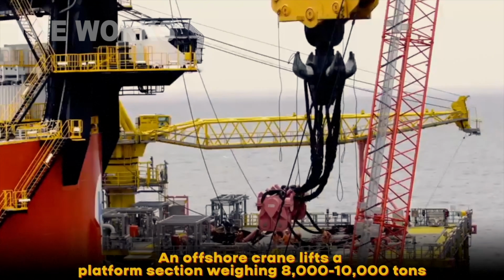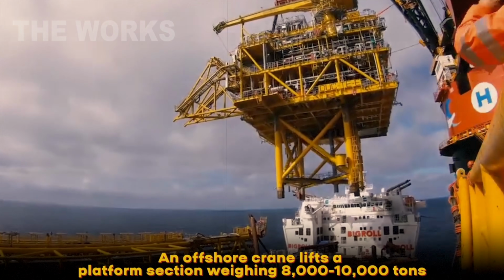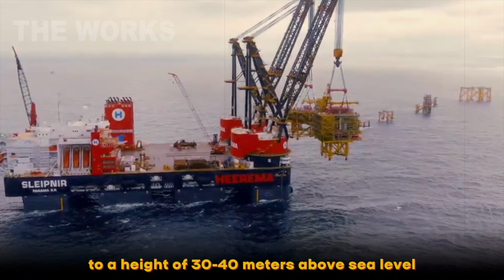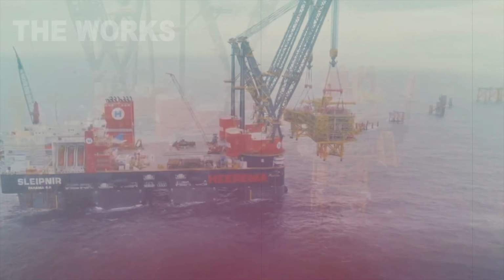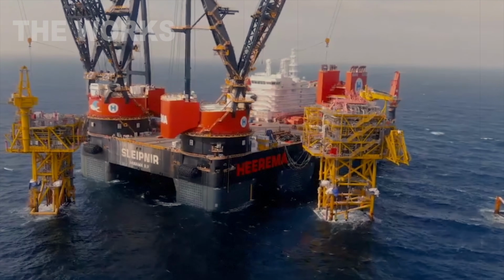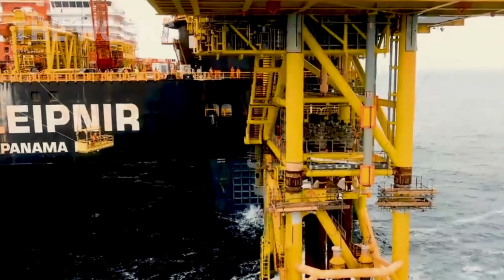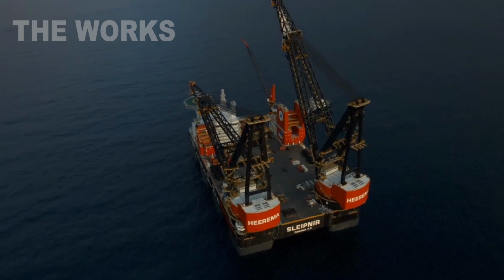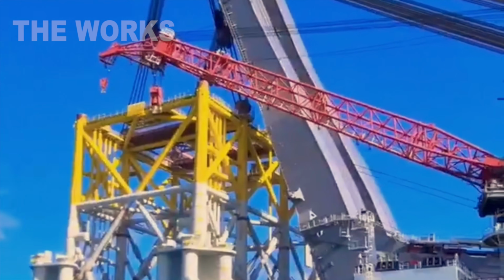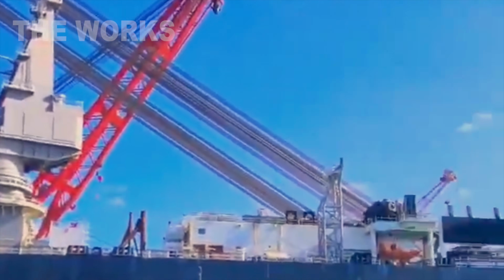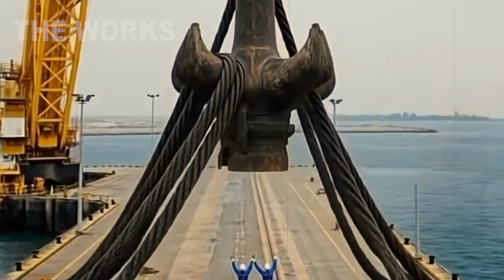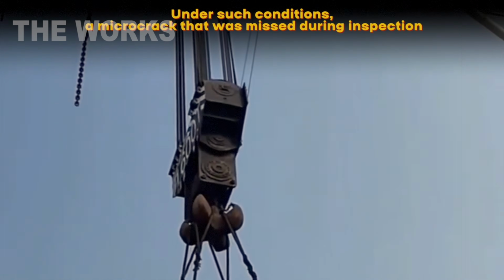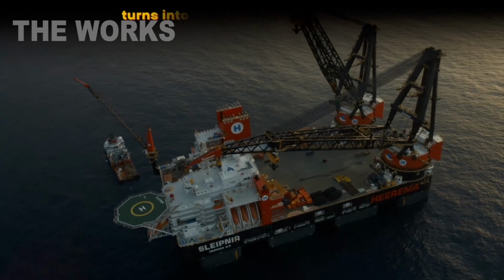An offshore crane lifts a platform section weighing 8 to 10,000 tons to a height of 100 to 130 feet above sea level. Waves slam the vessel's hull, the crane sways, the load cycles constantly, slackening slightly, then building again. These cyclic loads are especially dangerous. They make cracks grow even when the overall stress stays within design limits. Under these conditions, a microcrack that slipped past inspection turns into catastrophic failure within weeks.